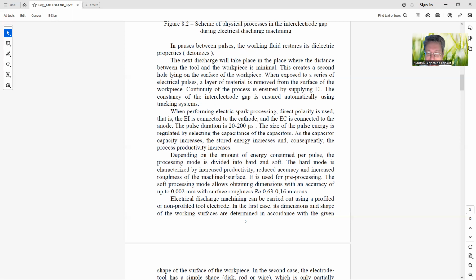Depending on the amount of energy consumed per pulse, the processing mode is divided into hard and soft. The hard mode is characterized by increased productivity, reduced accuracy, and increased roughness of the machined surface. It is used for pre-processing. The soft processing mode allows obtaining dimensions with an accuracy of up to 0.002 millimeters with surface roughness Ra 0.63 to 0.16 microns.